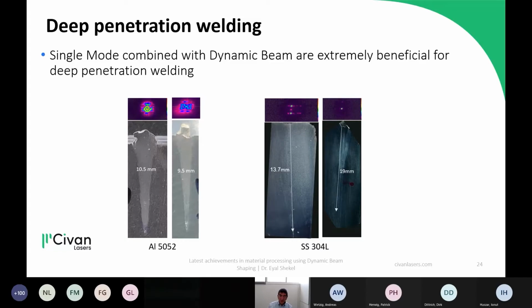Another very important field that we see as a substantial advantage for our laser is deep penetration welding, because we can provide extremely high power at single mode, so you can have very nice deep penetration welding. But again, as probably many of you know, when you do that, you get a lot of porosity. But with the beam shape, and with some dynamics, we can actually get rid of porosity. So here are just a few examples of deep penetration welding in stainless steel and in aluminum. We saw that we can get very deep penetration welding, but sometimes you get porosity. And by introducing some dynamics to the beam, you lose a little bit of the penetration depth, but you get a very, very good weld.